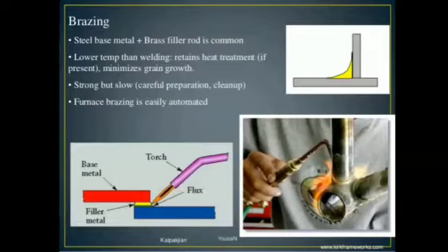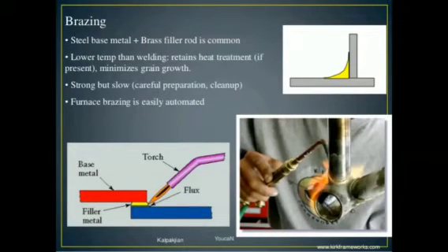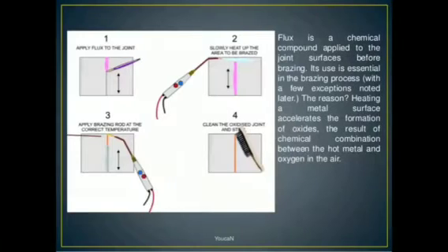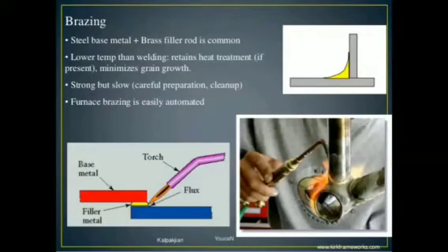So coming to brazing, the base metal is steel, and a base metal plus brass filler rod is common. The second important point is a lower temperature than welding. It retains heat treatment, if present, and minimizes grain growth. It is strong but slow: the joint is very strong, but the capillary action is very slow. Therefore, we require careful preparation and a cleanup action using flux, a chemical compound applied to the joint surfaces before brazing. That is the cleaning up operation. The last important point is that furnace brazing is easily automated.